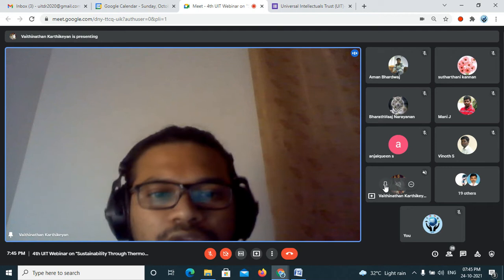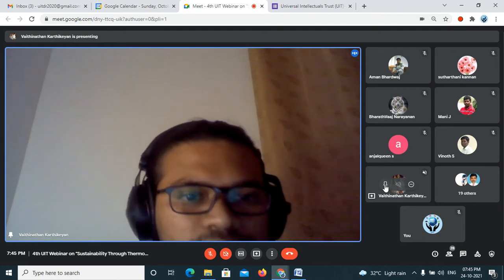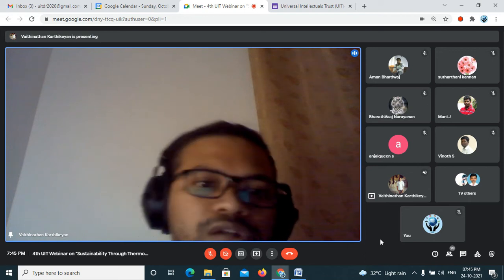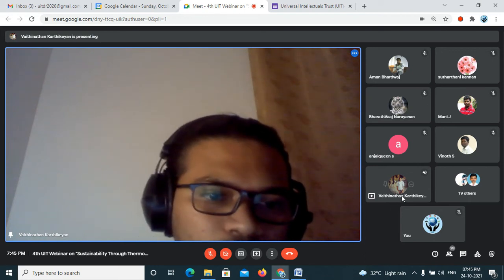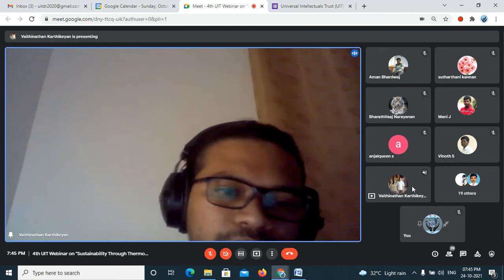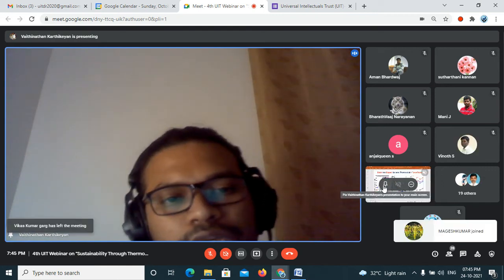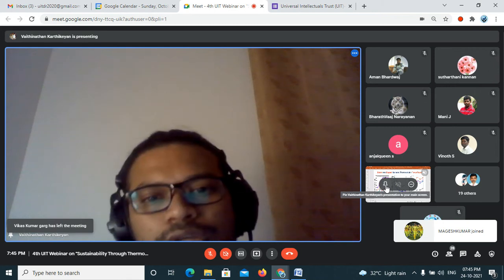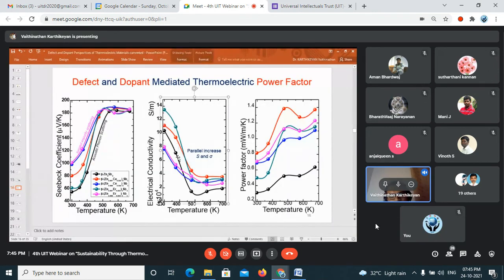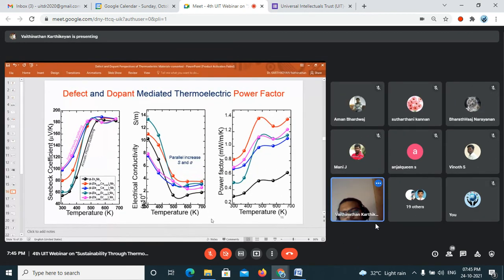And this is the Seebeck characterization. You can clearly observe the black one is the pristine one, and the others are doped cases. The black one is low for Seebeck, whereas for the doped cases it keeps increasing. And also in the case of electrical conductivity, second graph, you can see that with the dopant it starts to increase, of 0.3%.